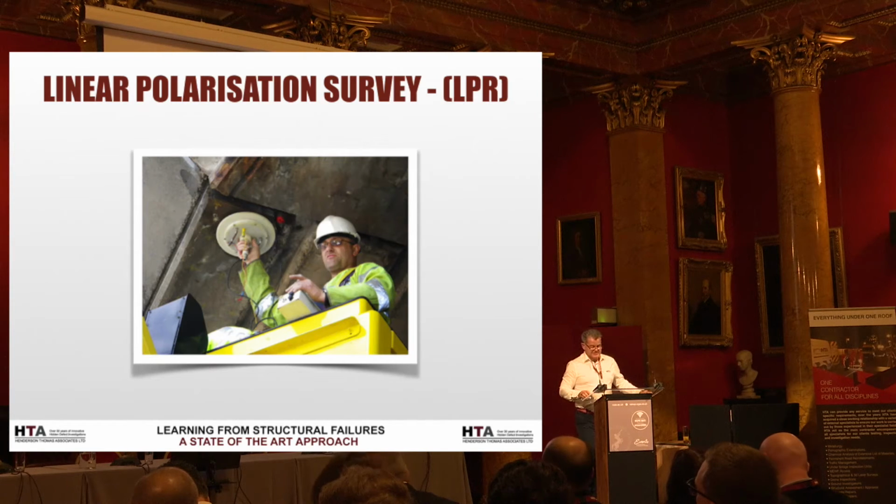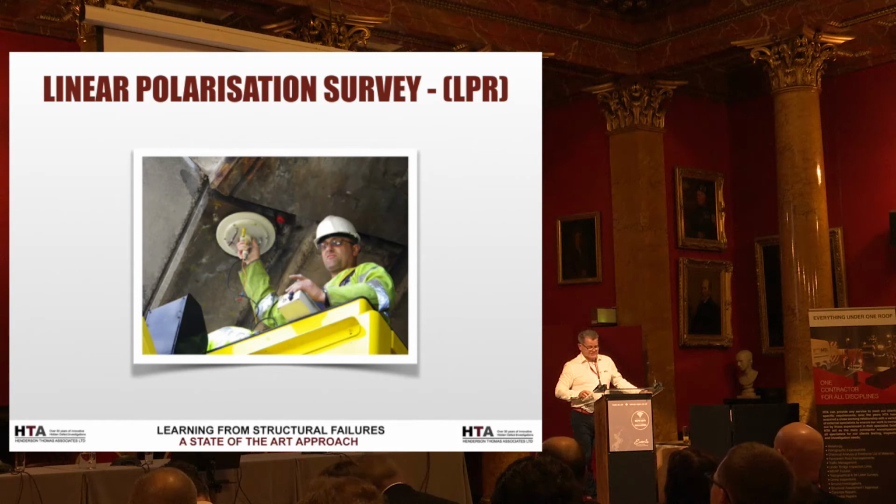What happens here is, as you can see in the photograph, the chap is holding a standard silver-silver chloride electrode, which would get you your standard half-cell reading. Around it, you can see what they call Bigfoot, which is a secondary anode. What this does is get around the problems that we have with increased moisture content on concrete. The reason we've got this photograph in here: these are pre-stressed beams on a bridge, and we'd had about a week or two of good weather prior to this job,